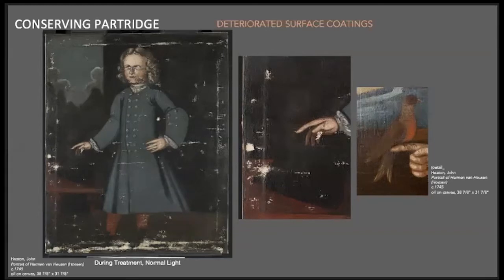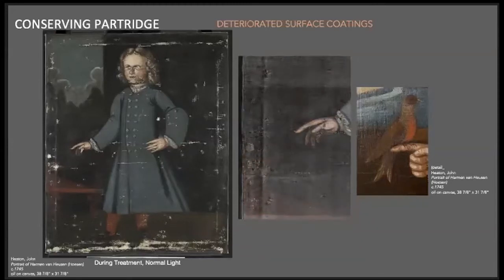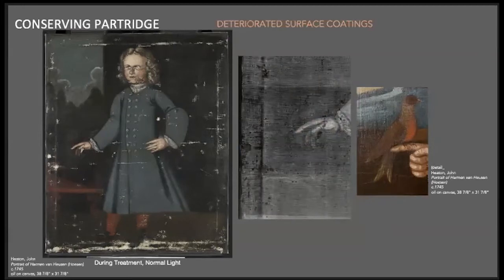In the hopes of uncovering additional information to help inform the reconstruction, the sitter's hand was X-rayed. The center detail image shows the transition from normal light to the X-radiograph. While the X-ray doesn't show the silhouette of the bird, I will be relying on the areas of abraded paint to match the bird in hue. In terms of the detail and anatomy of the bird, I will defer to another painting in the lab. Shown on the right is a detail of another portrait by Heaton that depicts a swallow-like bird, currently in the lab being treated by assistant paintings conservator Mary Holland.